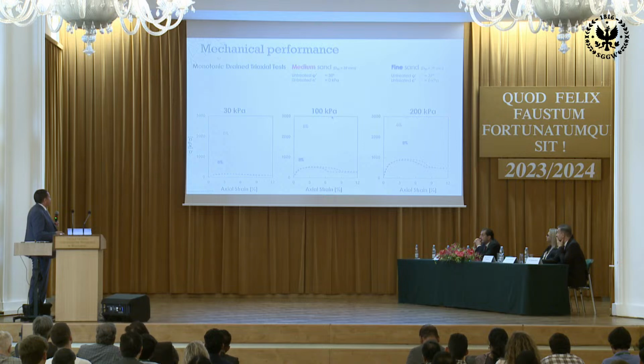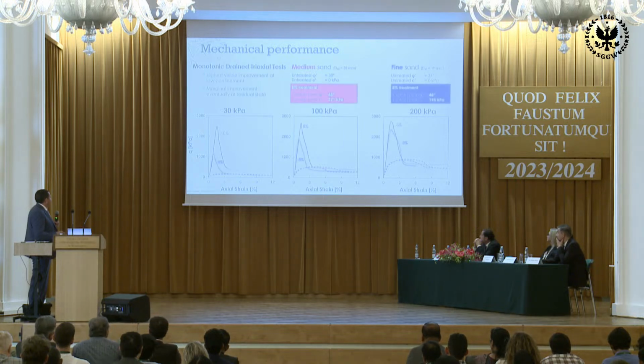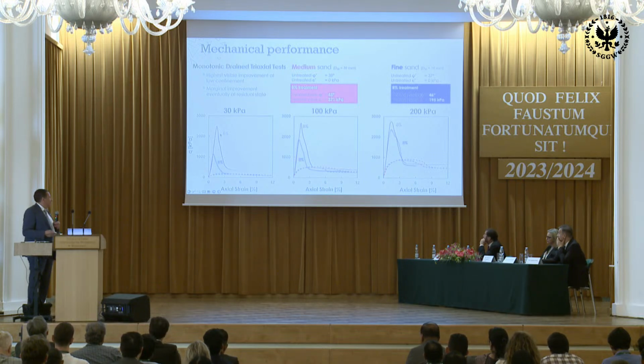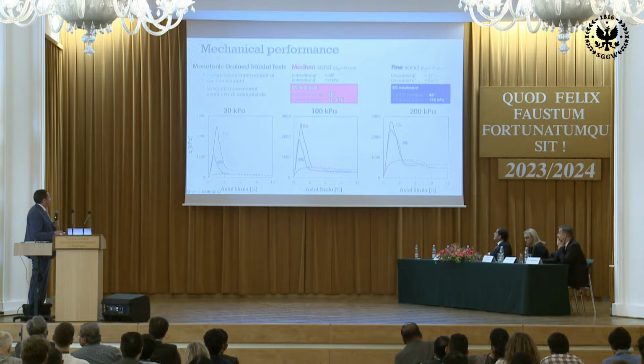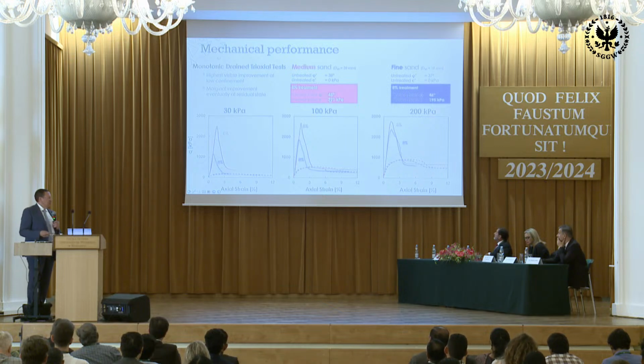We did also triaxial tests on the same type of materials. So you see here the shear plane for different confining stresses, and then after treatment, in this case, it's 8 megapascal. You see that we move from something like 200 kilopascal to more than 2,000 kilopascal of strength for those materials. When you look at the friction angle at the peak, it's not changing that much, but we are creating significant cohesion, almost 400 kilopascal in this case.